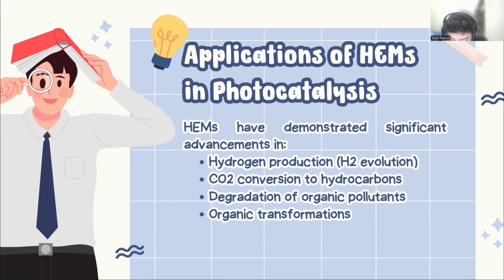Due to limitation in fabrication methods, existing reports on high entropy nitrides (HEN) are confined to thin films or powder. Lee synthesized ceramic nanofiber of HEN from liquid precursor via electrospinning and high temperature NH3 atmosphere nitridation. This marked the first preparation of HEN nanofibers and the initial application of high entropy ceramics in CO2 photocatalytic reduction.